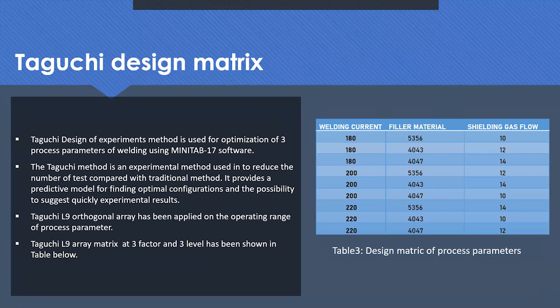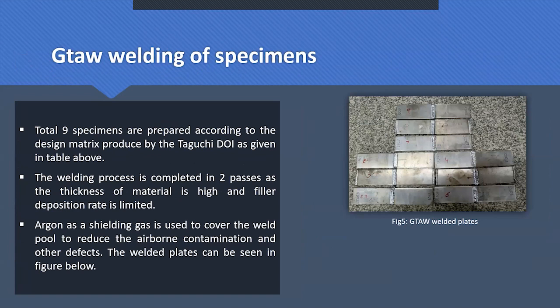For filler material, as we discussed, three different fillers have been used. For shielding gas flow, three different levels of gas flow have been used, starting from 10 liters per minute, 12 liters per minute, and lastly 14 liters per minute. These samples have been prepared according to the design matrix of Taguchi, and argon is used as a shielding gas for the shielding of the arc between the non-consumable electrode and workpiece.